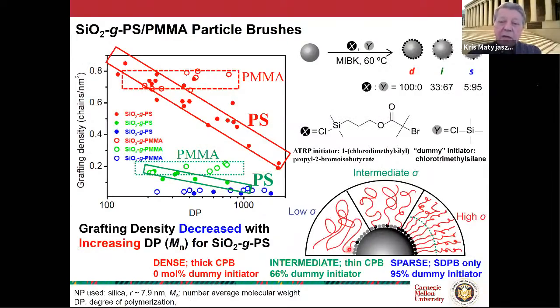So this is work done by Zhongyu Wang, and he tried to check how the grafting density on nanoparticles, starting with a very dense system with a grafting density of nearly 1 chain per square nanometer, going down to a very loose or sparse grafting, approximately 0.05 chain per square nanometer, and then having this intermediate part, how they would change with the degree of polymerization of PMMA or polystyrene.